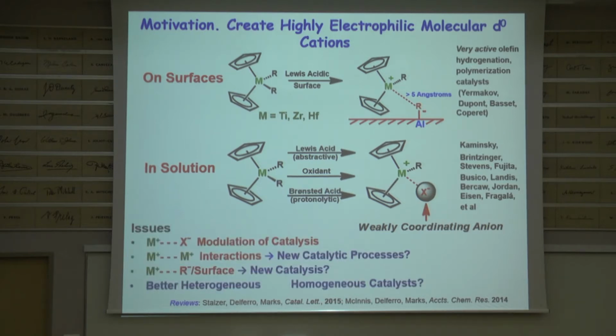And the questions that we'd like to approach today, and this is a general lecture for general audiences: what is the nature? If I put triflate there, I get no catalytic activity at all. If I put tetrafluoroborate or hexafluorophosphate there, the cation simply abstracts fluoride. Wow, that is a hot electrophile.